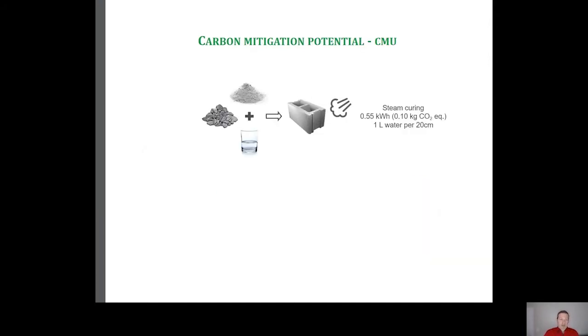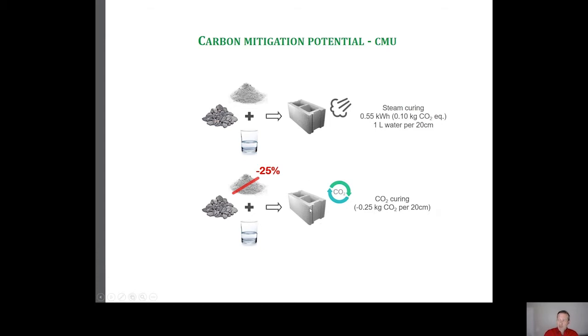If we're looking at typical ways of the curing process, you've got your steam curing, where you have your aggregates, your cements, your water, and then you add that steam effect, heat, and hydration. If you do the carbon cure version where you're just using carbon dioxide, in theory, you can reduce about 25% of your cement. Obviously, we're playing with different levels of that as well. You can use other supplementary cementitious materials like slags or blast furnace slags, fly ash, depending on where you are. Initially, what we're getting with using the CO2 is about a 50% reduction in the carbon footprint of making concrete. Now, we all know cement has a high footprint, but that's cement, and we use only 10 to 20% of our batch as cement. So making concrete itself does not have a huge carbon footprint, but the cement part of it does. It's important to keep note of that. When you make concrete, you basically just use pneumatics to push it together. We're not actually burning any fossil fuels.